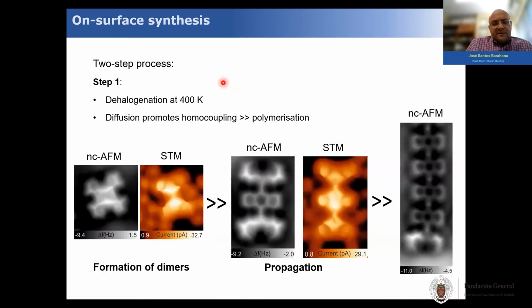This process occurs in two different steps. In the first step, you heat the reaction at 400 Kelvin, and you induce the dehalogenation of the molecules. Once the molecules are dehalogenated, they start diffusing through the surface, and once two molecules collide and find each other, they can form a dimer, as you can see here. Then the dimer continues diffusing until it finds another monomer. Here you can observe a trimer, and if we continue this diffusion and propagation, what we finally obtain is a long polymer.